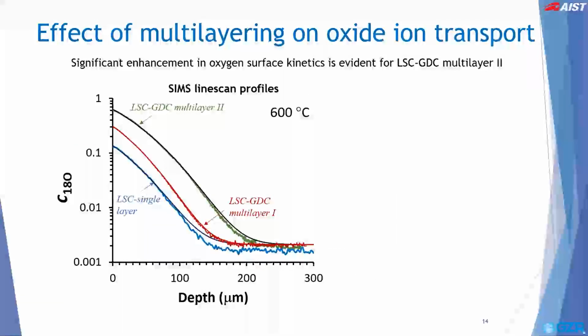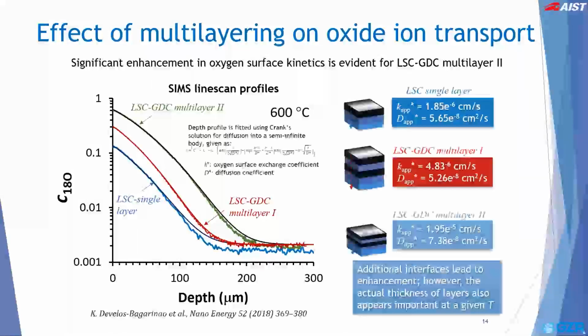This slide shows the comparison of the SIMS line scan profiles across cross-sections of samples with single-layer LSC cathodes in comparison with LSC GDC multilayers. You can see the differences in the relative amount of the 18O tracer between the single layer in comparison with the multilayer. From the fitting of the SIMS profiles, we extracted the apparent surface exchange coefficient, or K star. We found an improvement in K star for the multilayers by almost 1 order of magnitude.